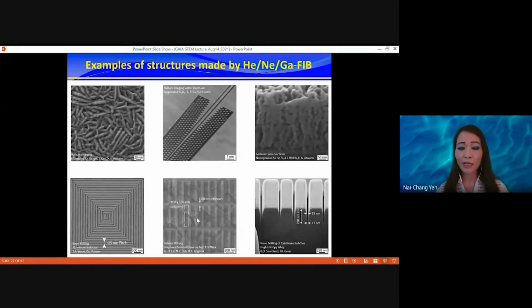And these are single atom layers. I mean, this is graphene, and you develop it into tiny, tiny structures using the helium beam, because the helium beam doesn't cause a lot of damage, and graphene is only one atomic layer of carbon. If you're not careful, you can cause a lot of damage. This is graphene on a substrate, so you can see the feature. Here you have a graphene layer, and here you do not. You removed the graphene. So you can see that these are used for very interesting devices.